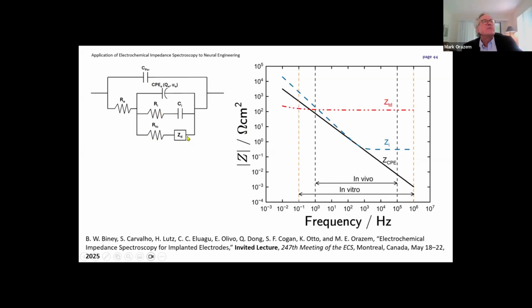So we can take the parameters we extracted in vitro and plot them on this plot of magnitude versus frequency. What we're seeing here, the black line, is what we see for the flat surface. This dashed line here is what we see for the iridium. And this red line here is what we see for the oxygen reduction. So when we're making measurements in vitro, we're using a larger frequency range, and we can begin to see this feature over here, because when you're looking at things in parallel, it's the smaller impedance that we're seeing. So we were able to capture this impedance of the reaction when we had a larger frequency range.